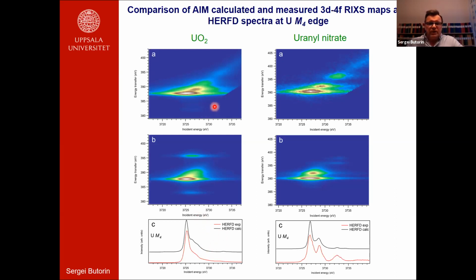But what I would like to point out here is that you can see in the experimental data these weak transitions, which correspond to transitions calculated due to 4f-5f interaction in the final state. So this is the final state effect here. And the other counterpart is not here because the region measured here goes like this, I think, if I remember correctly. So these transitions are on the boundary to be detected, and we need another experiment to check that.